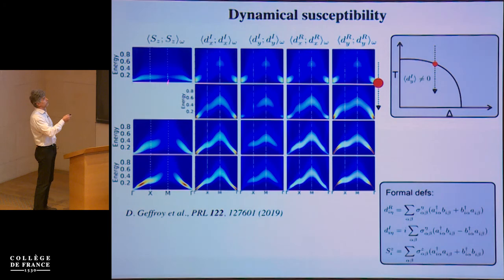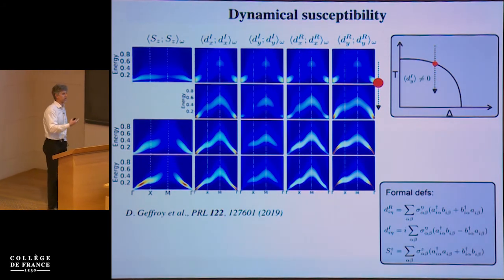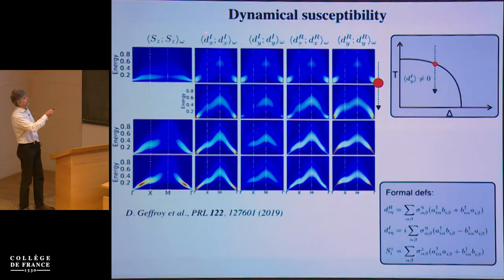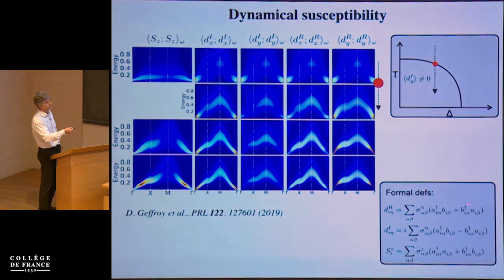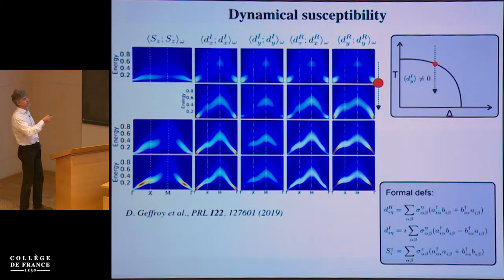This left column corresponds to the spin-spin correlation function, so this would be the spin dynamical structure factor, and these different columns correspond to different excitonic susceptibilities. If you're interested in the exact form, these are the corresponding operators. These essentially describe a dispersion of an exciton in the normal phase.